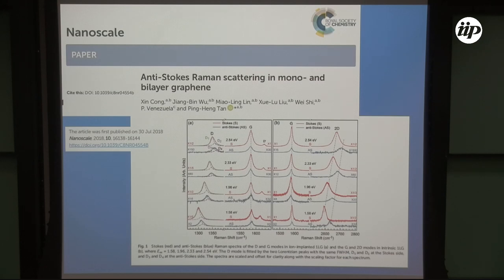when you do Raman spectroscopy, you can create phonons, or you can also annihilate them. So the anti-Stokes spectra comes from the annihilation of phonons. So here are the experimental results by Xin Cong. Usually people plot the Stokes peaks in the positive part of the graph and the anti-Stokes peaks in the negative part of the graph. But in this case, we display them in the same graph in order to compare better. Also, what we need to do is increase the intensity of the anti-Stokes peak here in the figure, because usually the anti-Stokes peaks are much, much less intense.